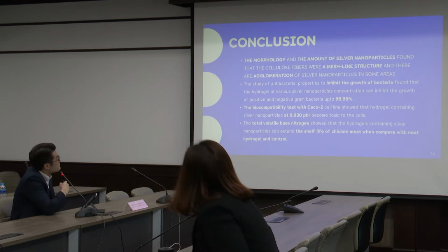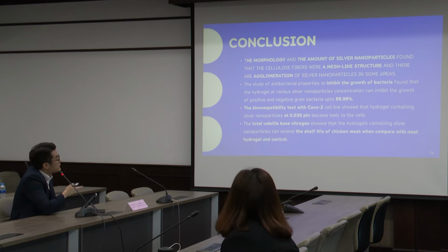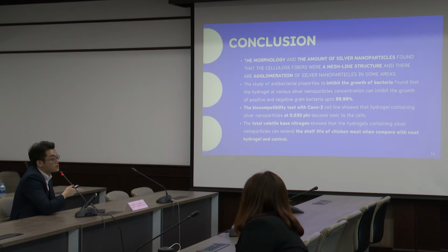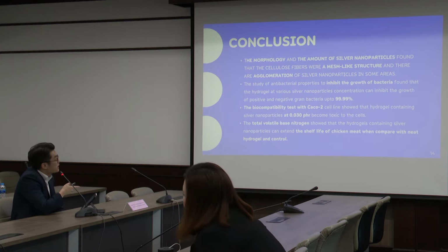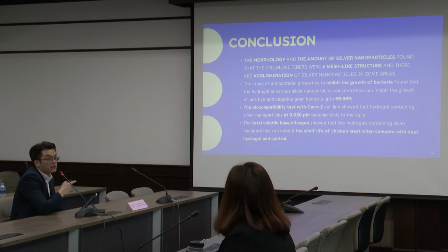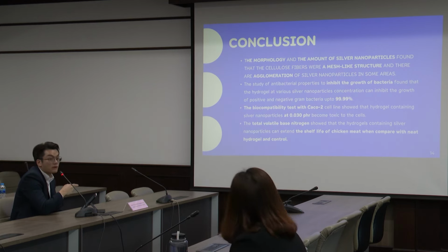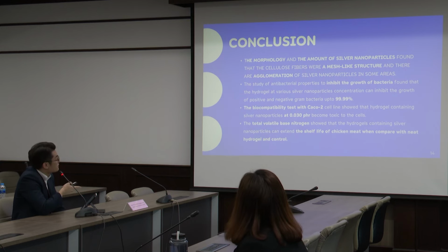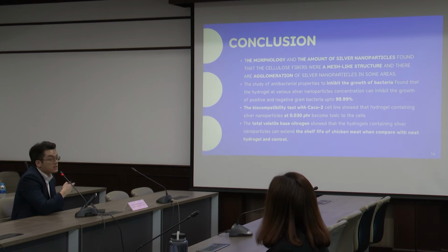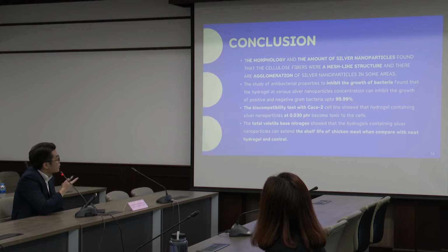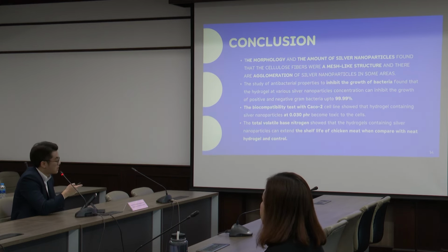So in conclusion, we succeeded in preparing the cellulose hydrogel coupled with silver nanoparticles, and the condition of about 0.015 phr is the best condition for use as active packaging because it can inhibit both Gram bacteria, is safe compared with the Caco-2 cell line, and extends the shelf life.